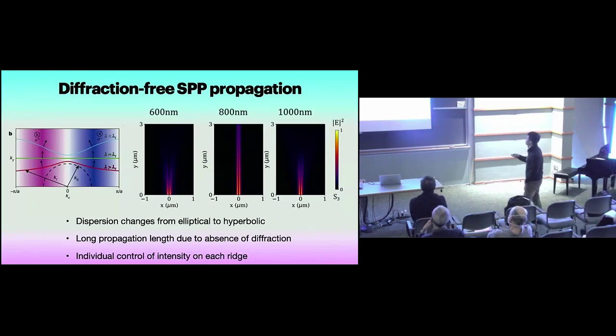So this is the simulation where we show that in the hyperbolic and elliptical regions, the beam would diverge. But in this dispersionless region, the beam will propagate along a single groove. So this is actually just a single groove, and it is concentrated on this single groove. So at this particular wavelength, you can deliver plasmonic power very efficiently because it doesn't disperse into other gratings. So it's confined only on a single grating. And this allows us to also potentially control individual gratings, right? So I can potentially vary the intensity only on this grating and not on the other grating.